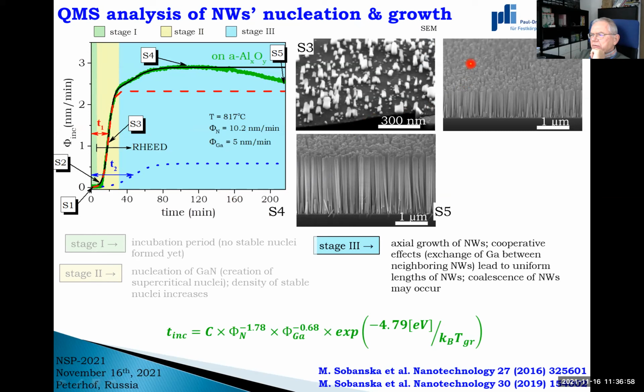Okay, and finally, this was the nucleation stage, and finally we are at the stage of elongation. So we get a nice system of nanowires. This curve decreases here, and this is because we observed at some stage coalescence of wires, and this is how we explain this decrease here.